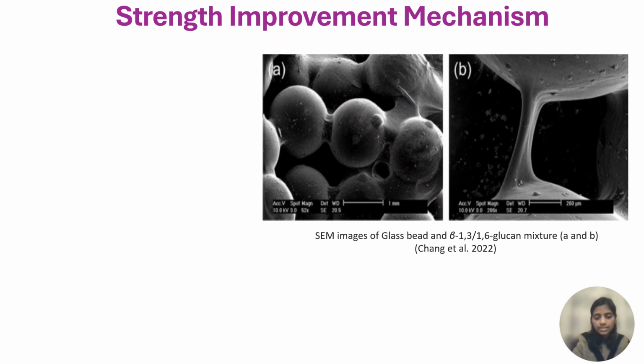Here you can see the SEM image. SEM is scanning electron microscopy, which gives very high resolution images. You can see glass beads which are mixed with beta glucan biopolymer. Beta glucan forms a hydrogel, and the hydrogel bonds two glass beads together, and also forms a kind of film or web that coats and connects the particles. So that's the glue-like effect that helps to bind the soil particles together.